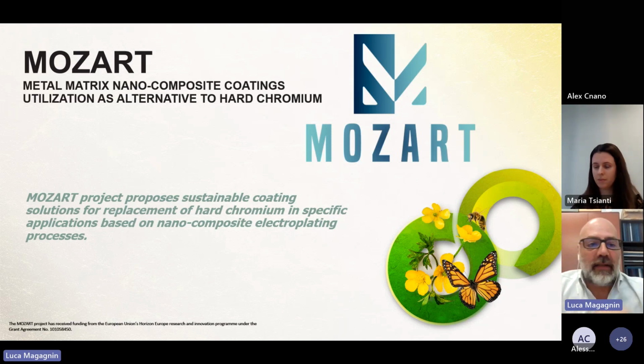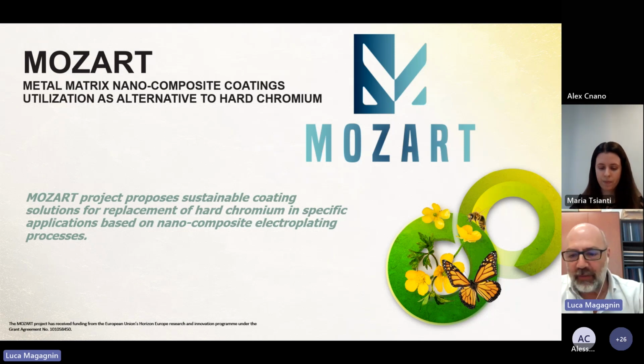Mozart, as you see, is aimed at the implementation of nanocomposite coatings in order to find an alternative to hard chromium. Even in the title you can see some words that are typically not associated with the green approach. So hard chromium plating is seen as a process not exactly environmentally friendly. In the previous presentation by Alessio, hexavalent chromium was mentioned, and also here, of course, for hard chromium plating, typically hexavalent chromium electrolytes are used.